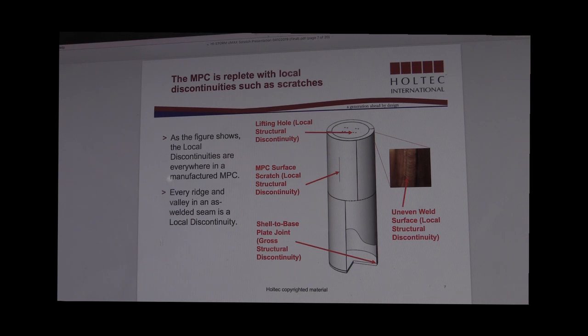is a stress concentration that affects the stress and strain distribution through a fractional part of the wall thickness. And it also does not affect shell-type deformation. It typically doesn't cause any visible distortion of the shell. Examples of a local structural discontinuity may be a small radius, small fillet radius, a small penetration or opening, and in slide 7, we show a couple other examples that are specific to the MPC itself.